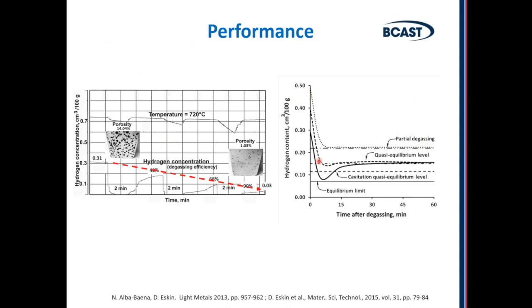But if you want really to have very pure melt with almost no hydrogen or very low concentration of hydrogen, and you achieve very deep degassing, you need to be aware that you need to use the melt right away. Otherwise, it will regas and absorb hydrogen from the atmosphere. Just to tell you that hydrogen comes into liquid aluminium from moisture. So humidity in air, H2O, reacts with aluminium to produce aluminium oxide, which remains on the surface of the melt, and hydrogen, which is dissolved in aluminium.